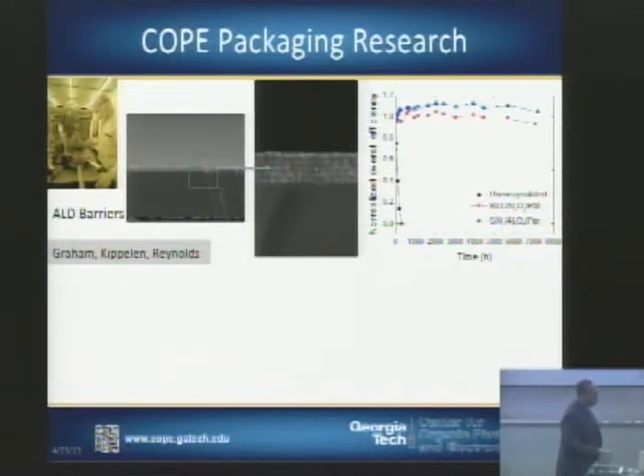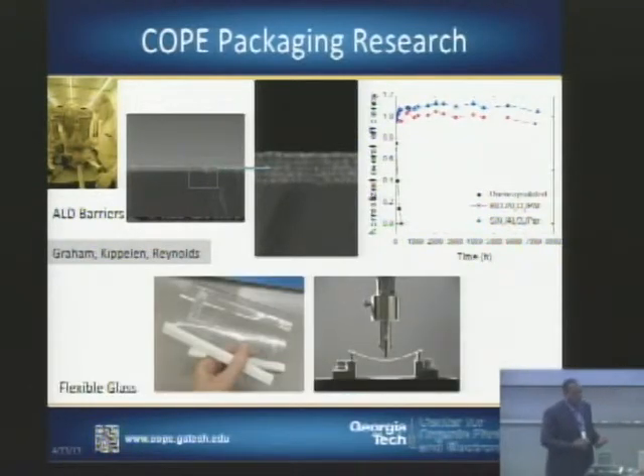And in addition to this, more recently we have been working with outside companies to look at things like flexible glass. So here now the issue is not necessarily making an ultra barrier, but how do you process on these particular structures. There's a little bit of an issue of fragility. If anyone has actually worked with these, you'll notice that while they're showing nice pictures here in terms of the ability to flex these substrates, they are difficult to handle. And so how do you go about doing the sealing process in order to protect your devices? So we are doing some work to compare the ability to process on these particular substrates as opposed to having your normal, say, polymer-based substrates with the ultra barriers.